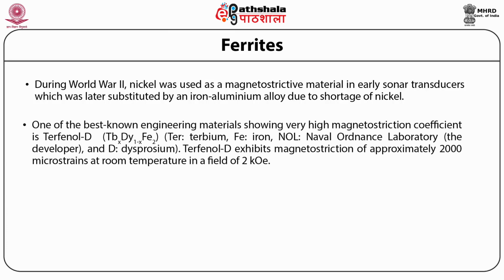One of the best known engineering materials showing a very high magnetostriction coefficient is Terfenol-D. Terfenol-D exhibits a magnetostriction of approximately 2000 microstrains at room temperature in a field of 2 kilo-oersted.